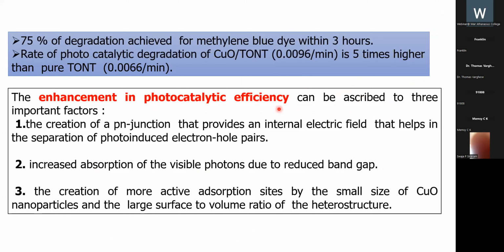The enhancement in photocatalytic activity can be ascribed to three important factors: the creation of a PN junction that provides an internal electric field that helps in the separation of photo-induced electron-hole pairs, increased absorption of visible photons due to the reduced band gap, and the creation of more active adsorption sites by the small size of copper oxide nanoparticles and the large surface to volume ratio of the heterostructure.